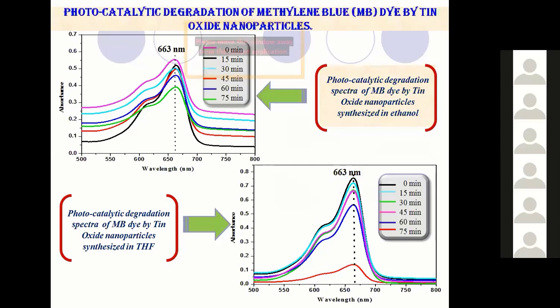In our laboratory, we have performed these experiments. We have mostly used methylene blue dye as the test contaminant, and sometimes also rhodamine dye. It has been seen that the water was purified. The photocatalytic activity also depends upon the particle size. When the particle size was reduced from 13 nanometer to 2 nanometer, the photocatalytic activity kept increasing with the decrease in particle size up to a certain size.